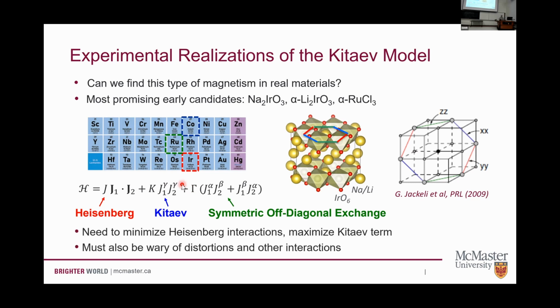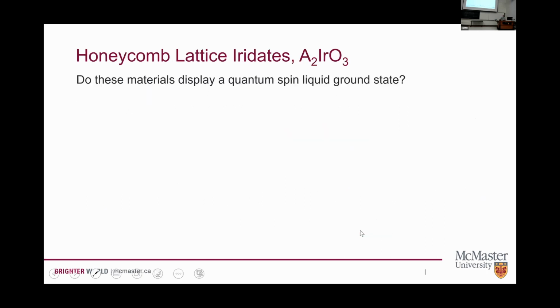So we want to try and find or design materials that have minimal Heisenberg interactions, that have as much Kitaev as we can put into them. And we want to watch out for other types of distortions or other interactions or hopping effects that might get us away from this nice clean limit. So if we want to see if these materials are really Kitaev model materials, the easiest thing we can do is cool them down to low temperatures and see if they become quantum spin liquids.